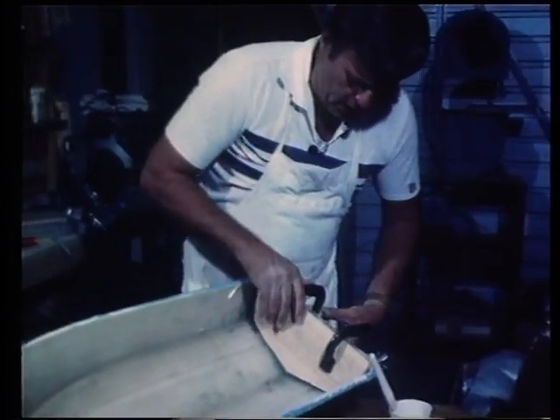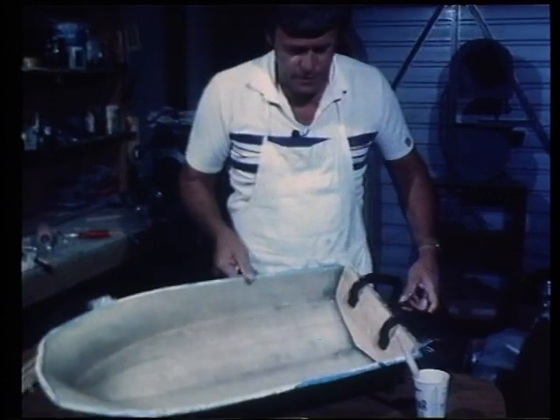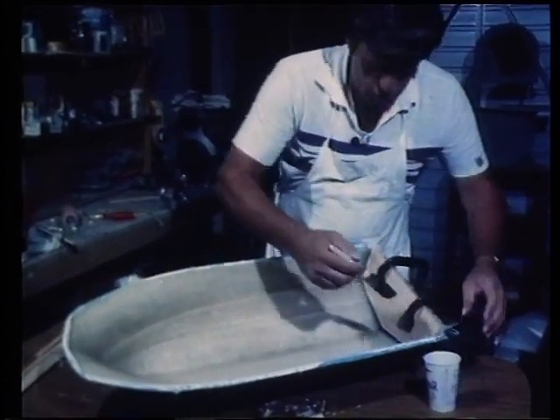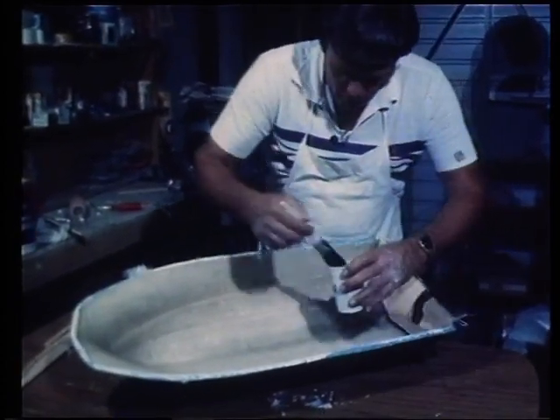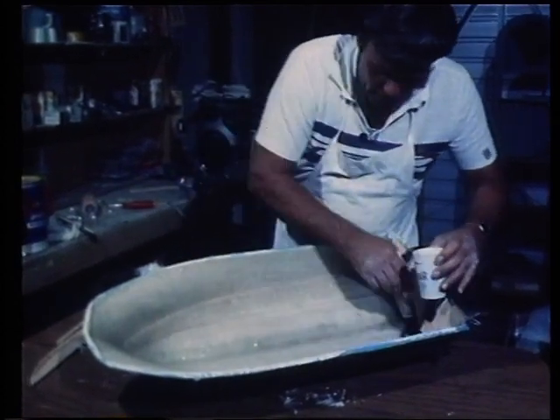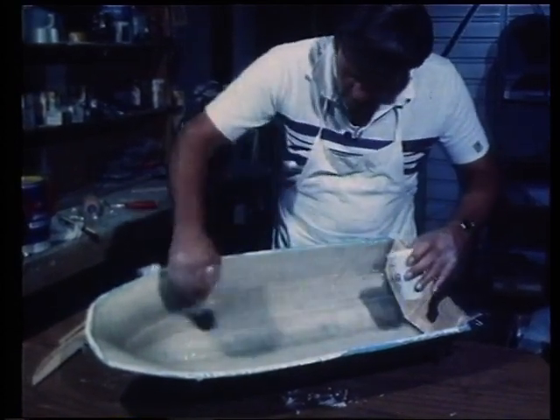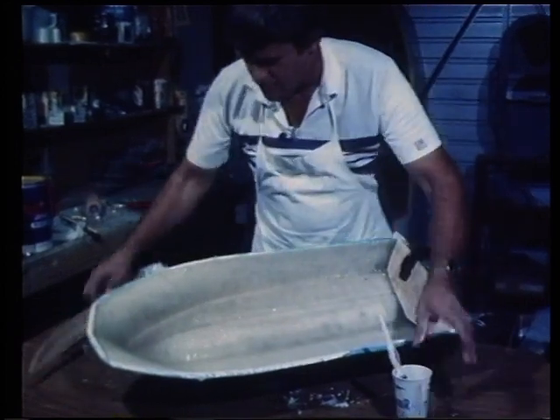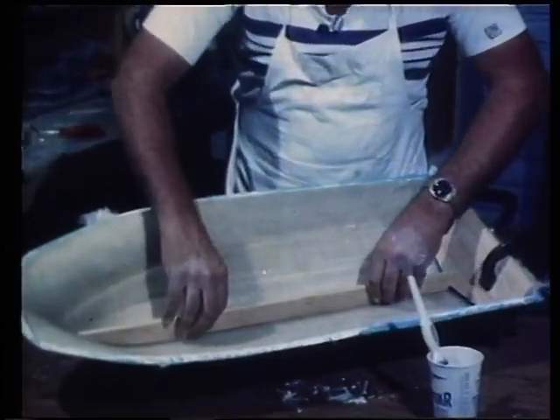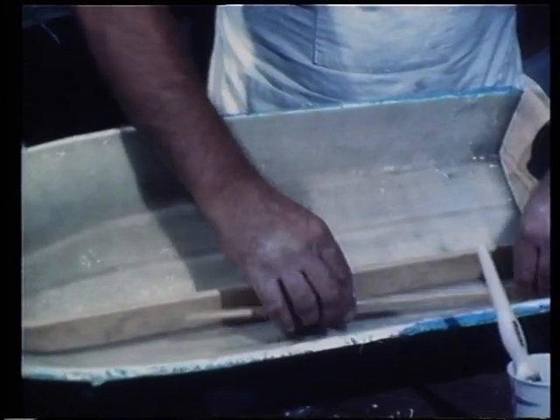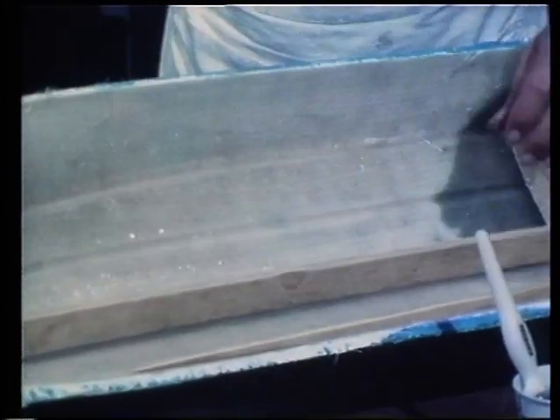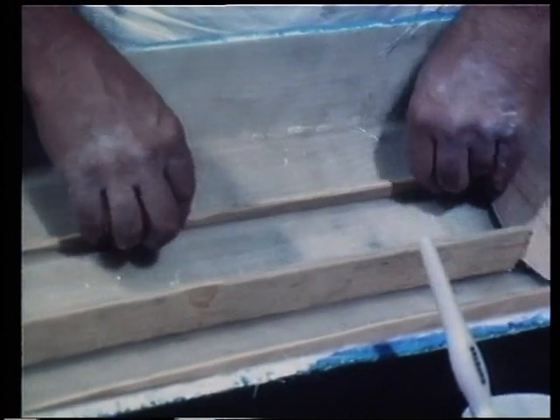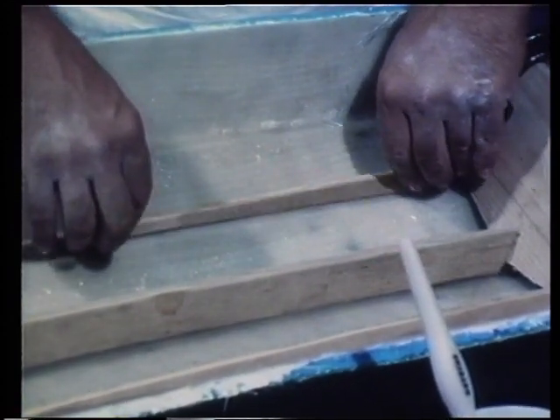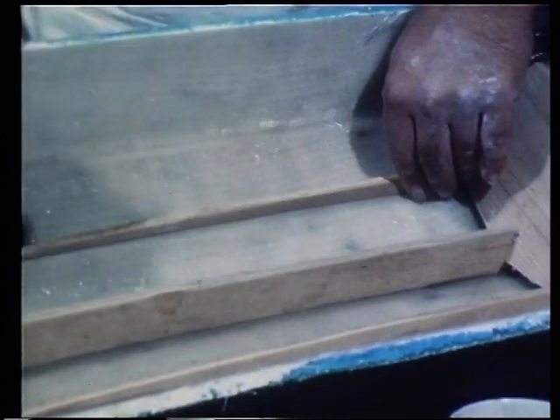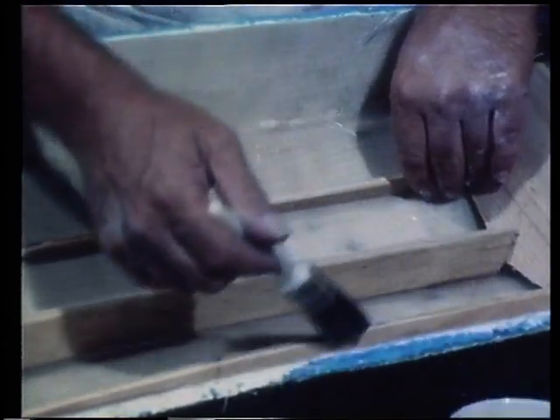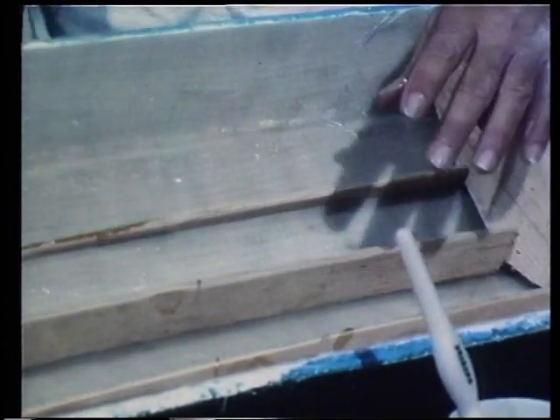Generally, with a full-size boat, the plywood has a sanded surface. If it does have a sanded surface, make sure that you rough it up with a disc sander before you apply it. Now, I'm just brushing some resin in there. Again, pretty well similar to the technique used for a larger boat. I've prepared the timber stringers, the longitudinal stringers, which I just drop in there and set them in the resin that I've put in. Now, that one probably will be a bit reluctant. No, it'll stay there. So we'll put a bit of resin around to stick them in. They have to be held solidly so that we can continue the bonding process.